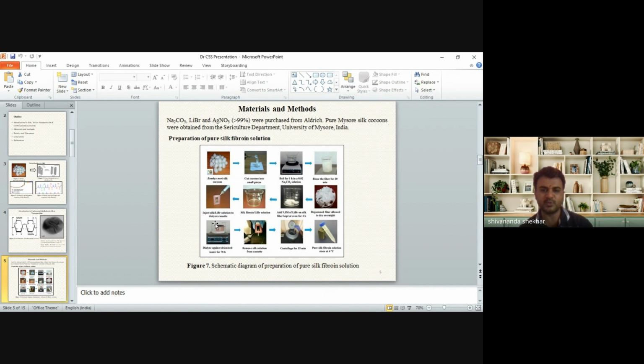Then we removed the solution from the dialysis cassette. Then we centrifuged it for around 15 minutes. In this dialysis, a very small porous membrane is there. Through that porous membrane, all these toxic lithium ions come out of the dialysis cassette. So that we get the pure silk fibroin solution for further experimental work. This is a schematic representation of the preparation of silk fibroin solution.